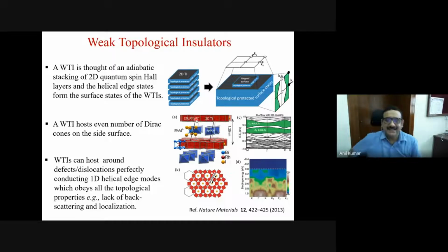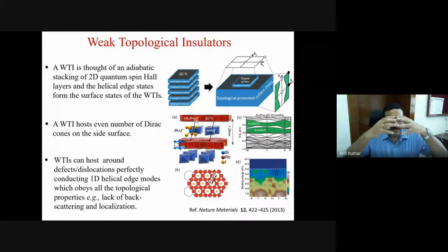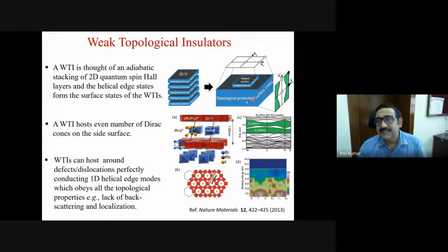So then let me just introduce you to another material which is not at all studied well, which is called weak topological insulator. In the other topological insulator, I said that the bulk is insulating and the surface is conducting. But in this kind of a weak topological insulator, only the side surface is conducting. So the side surface gives you the topologically protected surface state, whereas the top surface is a gapped surface. It's a dark state, something like this.